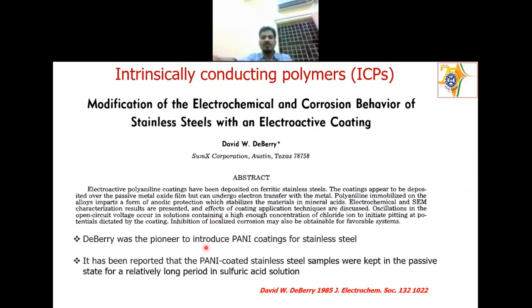This is one such paper, the first paper, which appeared in 1985 in the Journal of the Electrochemical Society by David W. DeBerry. He was the first who introduced PANI-based coatings on stainless steel. He found that when you apply an electroactive coating on stainless steel, there is an improvement in corrosion protection in the sulfuric acid medium. The sample was kept in the passive state for a relatively longer period in the sulfuric acid medium when you have a PANI-based coating on the stainless steel.